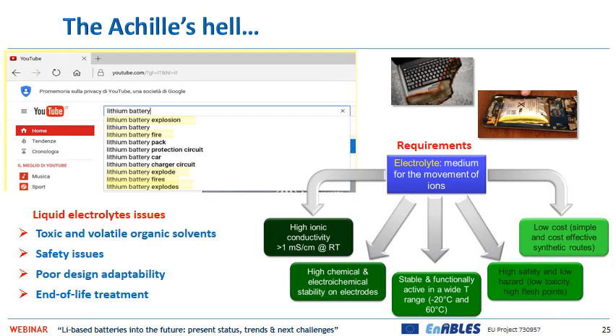Currently, most of the commercial lithium-ion batteries use liquid electrolytes, which have high ionic conductivities, allowing for fast charging. However, the use of these electrolytes is the main cause of the safety issues, like fire hazards, see the problems with smartphones, notebooks, but also electric cars, and low sustainability. These issues come from the chemical nature of liquid electrolytes that are based on organic solvents, which are toxic and volatile and are also prone to leakage.